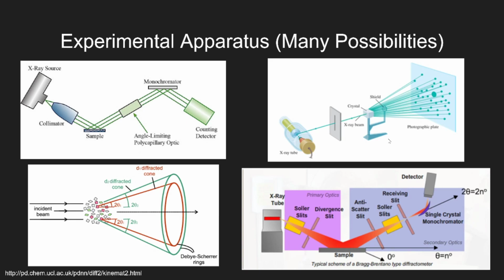If your grains aren't actually small enough, then you're too close to the original system where you just have a single crystal. So there's a range in which powder diffraction is pretty solid, and anything larger than a few micrometers, you can usually orient into a single crystal X-ray diffraction experiment. And then also there's some information loss from equivalent reflections.